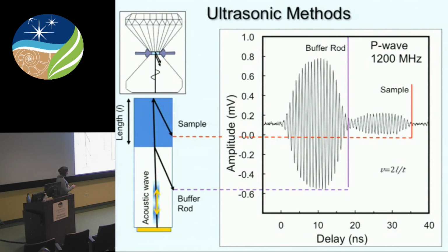And so you can see the reflection of the wave coming back from the buffer rod sample interface, and then again from the far side of the sample. And so we can use this to tell us what is the travel time of the wave in the material. If we know the sample length, then we can calculate the velocity. So velocity is 2 times length over the travel time. And we do this at high pressure in the diamond anvil cell.